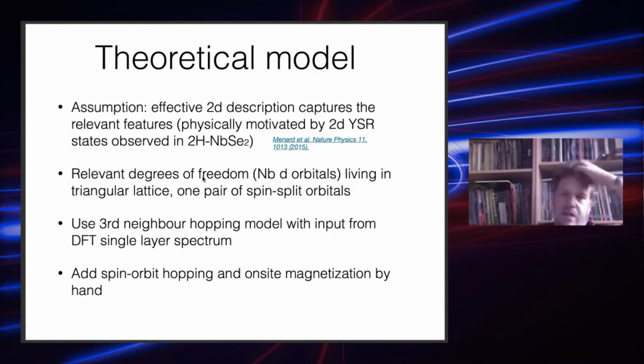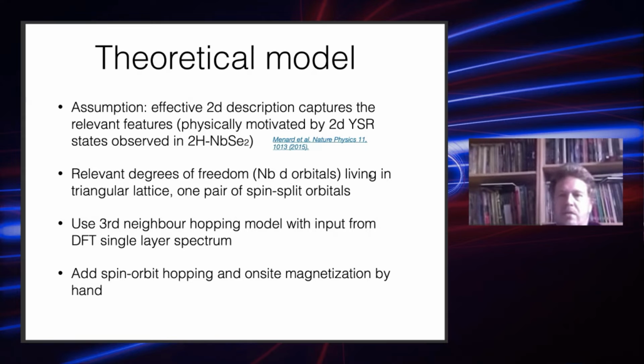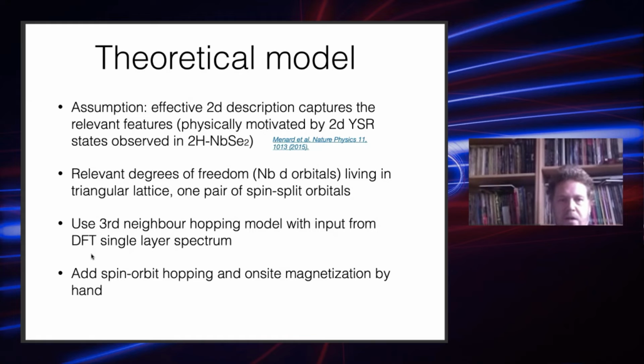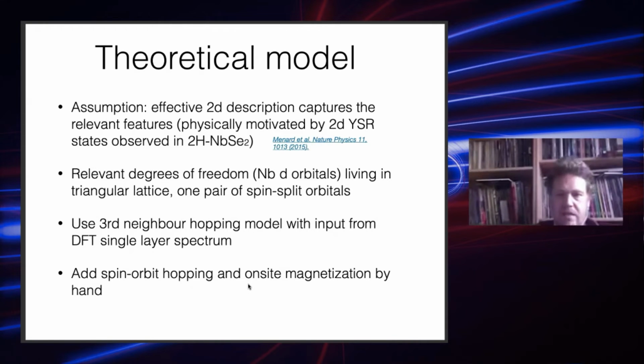So the relevant degrees of freedom in the theoretical model are niobium d orbitals that are living on a triangular lattice. So we have a triangular lattice, and then we have one pair of spin split orbitals on this triangular lattice. And to somehow mimic the real band structure, we are using a third neighbor hopping model, where we get the input parameters for the tight binding model from our DFT colleagues. And in the end, we add Rashba spin orbit coupling and on-site magnetization by hand. So the basic band structure features without magnetization and spin orbit coupling come from DFT, and then these are phenomenological fitting terms that we add, the Rashba spin orbit coupling and on-site Zeeman magnetization, which is a local magnetization splitting at each site.